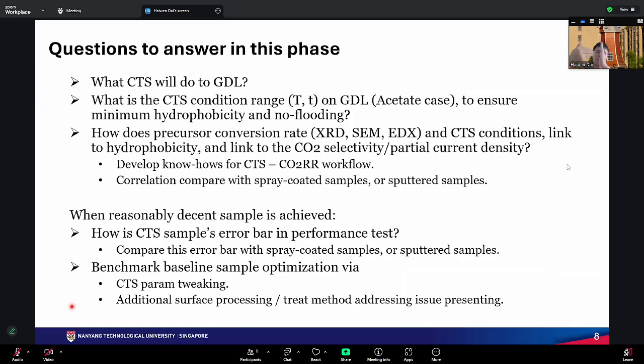If this surface leaks water, which means it is hydrophilic, water will penetrate through, flooding the whole gas chamber. So CO2 cannot directly contact the material with the catalyst. What we can only hope is that there is only a thin layer of water that can diffuse some CO2. There are still some people doing that, but it is not something mature. If this is fully flooded, then the reaction does not happen.